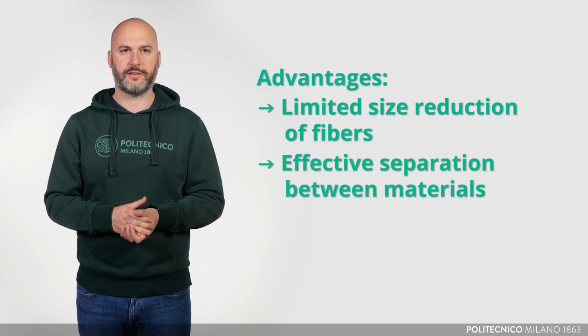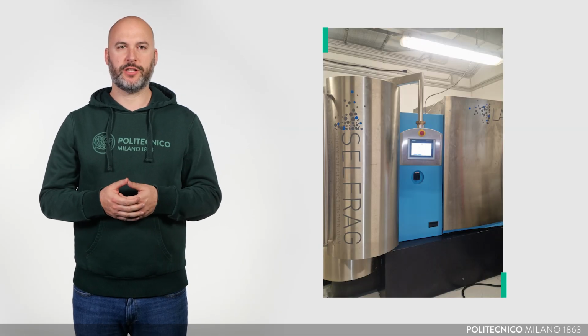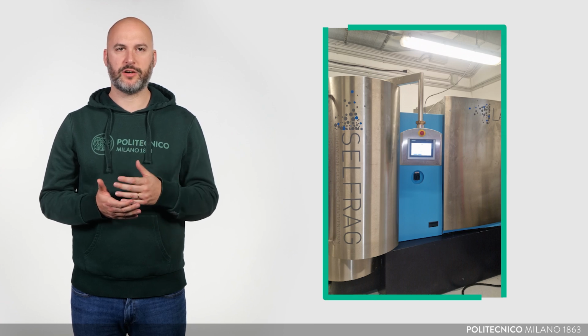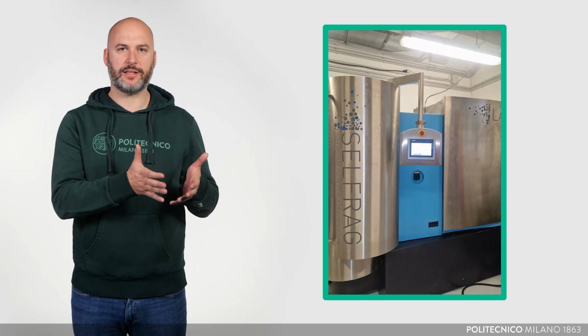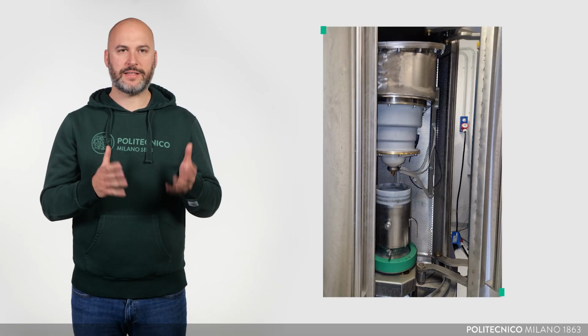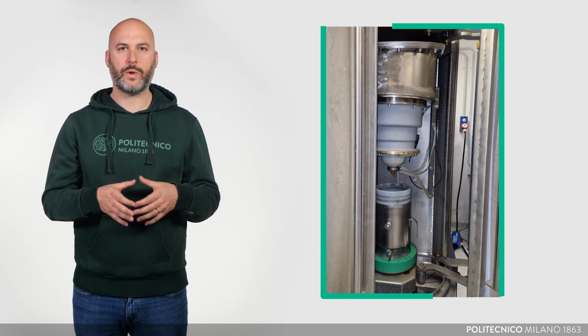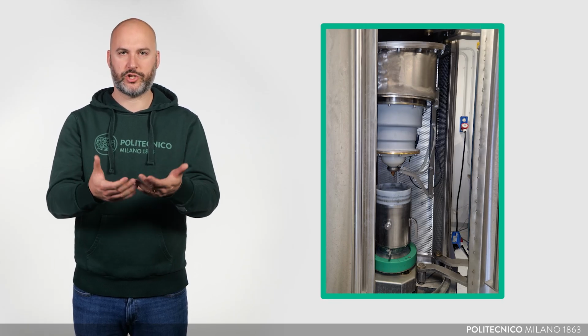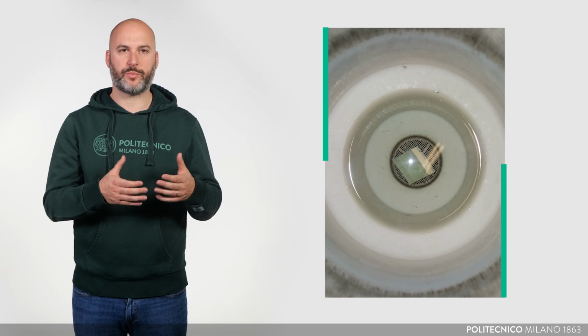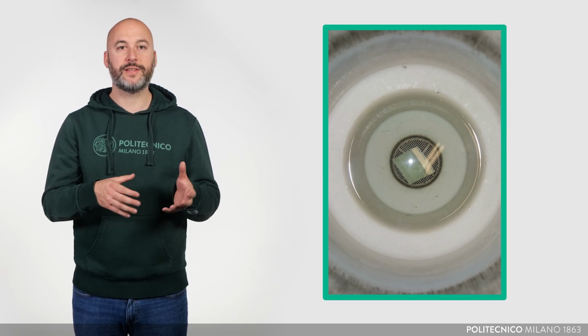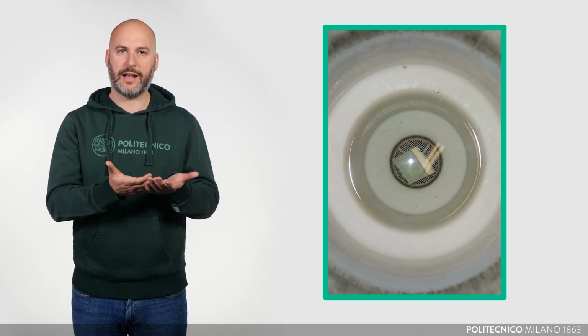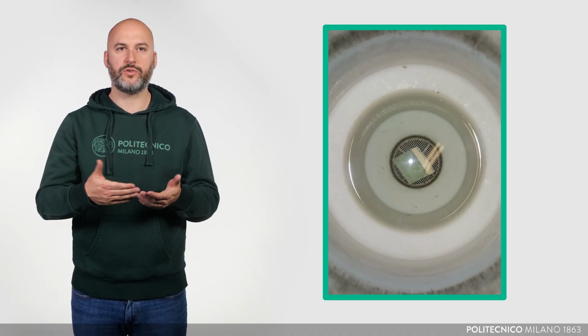The advantages of this technique are that it limits the size reduction of the fibers and it results in effective separation between different materials. The high-voltage fragmentation machine features a modified Marx generator and a series of capacitors that convert traditional electrical current into high-voltage current. These components can adjust the voltage using nitrogen pressure, generating a rapid current ramp-up with peak rise times under 500 nanoseconds. The material to be treated is placed inside the process vessel within the processing chamber, located at the front of the machine.